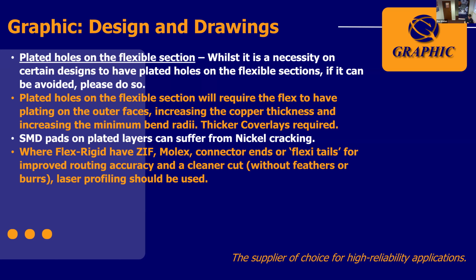Again, we see quite a lot of designs, and I'll show you an example straight after this, where we have drilling on the flexible section. We have a flexible tail where they are also then assembling a component onto the flexible tail. Now, because you have that flexing of the flexible laminates, if it's plated and then you've got SMD pads on that tail, you can then effectively get some issues when it comes to the surface finish. So a universal finish that you will see is electroless nickel immersion gold. And what you can see on surface finishes being applied to the flexible laminates is you can see nickel cracking as a concern.